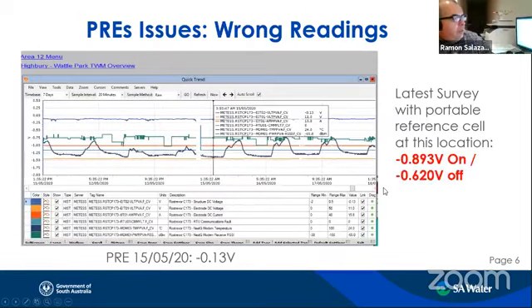And this is another example, another water main. So the reference electrode is measuring minus 0.13 volts, but the latest survey was 0.893 volts on, 0.620 volts off at that particular location. So obviously this 0.13 volts is really, really far from the point. And then you see there's like a straight line here, doesn't have much change. So then the question is, what's going on here? Is it just because it's dried out? Can we reactivate the reference electrode, or is there a problem with probably a broken cable? So that's why we probably need to investigate this.